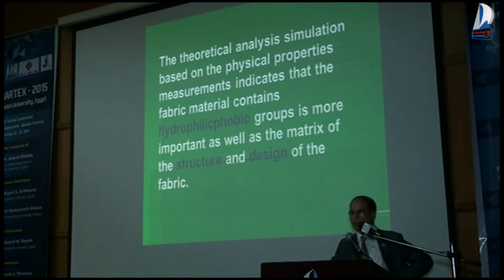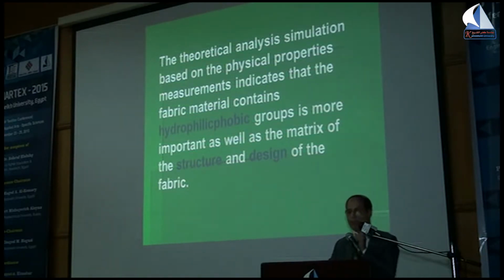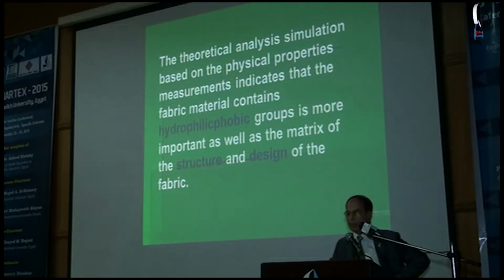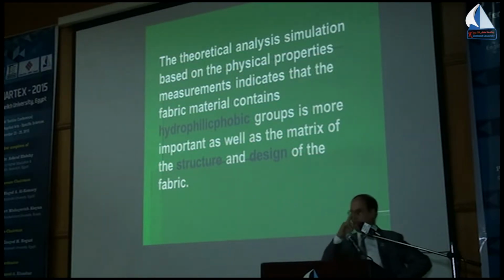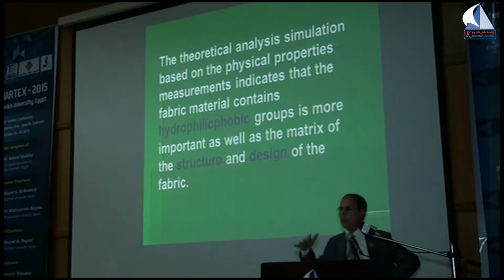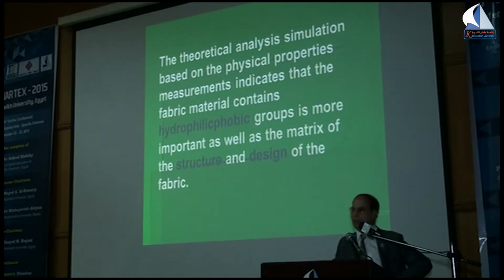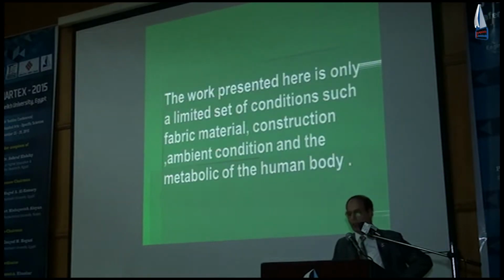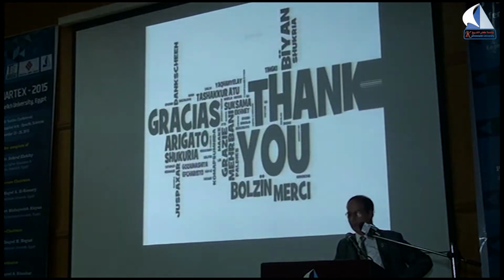Theoretical analysis and simulation based on the physical property measurements indicate that fabric material containing hydrophilic and hydrophobic groups is more important. I mean, not hydrophilic only, but hydrophilic and hydrophobic, the same as blended fabrics. These groups are more important, as well as the matrix of the structure and design. I mean, the plain weave is not better than the satin weave. The satin weave is very good because of the intermeshing and the void spaces between the fibers, fiber to fiber and yarn to fabric. The work represented here is only a limited set of conditions such as fabric material, construction, ambient condition, and the metabolic rate of the human body. Thank you.